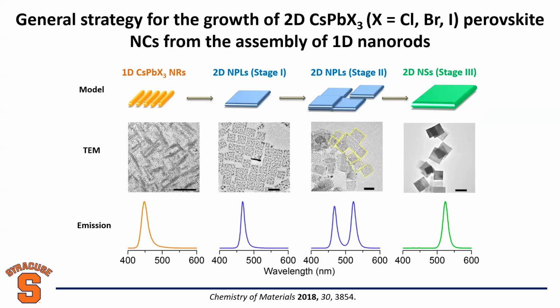Okay, so before our work, people could only directly make cesium lead bromide 2D materials, and we found this is a general method. We can make all halide nanoplatelets. We can make the chloride, bromide, iodide, everything. So this is the first general method to make 2D perovskite nanomaterials. Okay, so we addressed the first question: how to control shape for cubic phase perovskite?